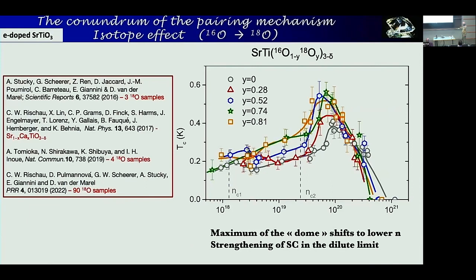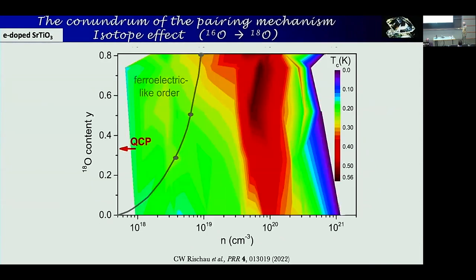You can see it somewhat better over here in this graph. This is the oxygen 18 concentration. This is the doping, and so there's a slight shift to the left, and in particular, there's an increase of Tc. Now, this is a significant result because the increase in Tc is the opposite of what you expect from BCS theory, and this effect is at least 10 times bigger than in BCS. So it's a completely different physics. So it was sort of correctly predicted, but there was a problem with that.